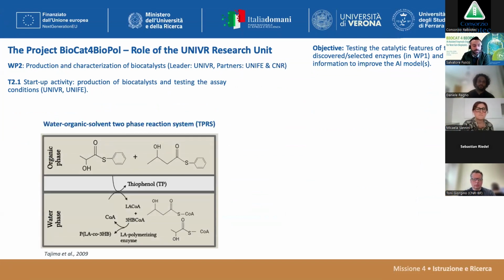We used a water organic solvent two-phase reaction system. In the organic phase, the precursor undergoes a transesterification reaction with the CoA present in the water phase, so we can have the production of the monomers that are used by the enzymes that polymerize the polymer. We got these materials from Daniele's group, and we set this condition in order to have the recycling of the CoA at each reaction, so it could transesterify every time with a different monomer.